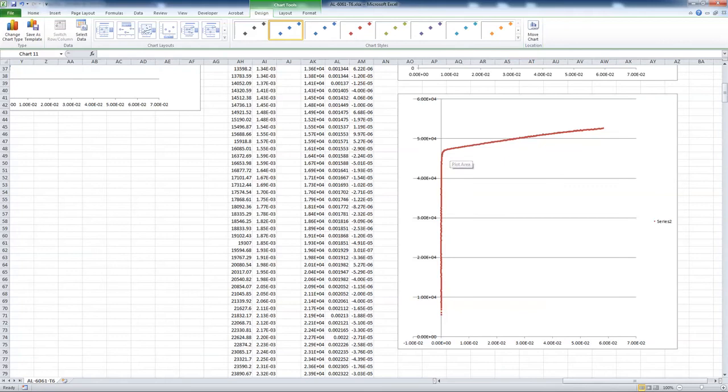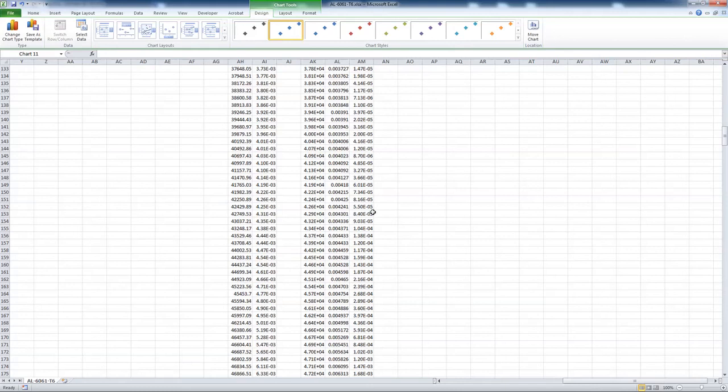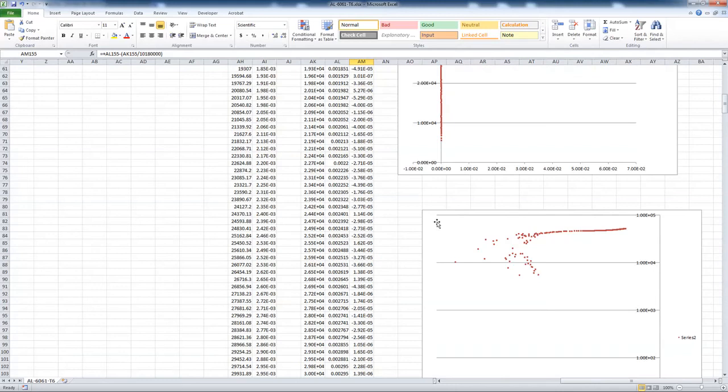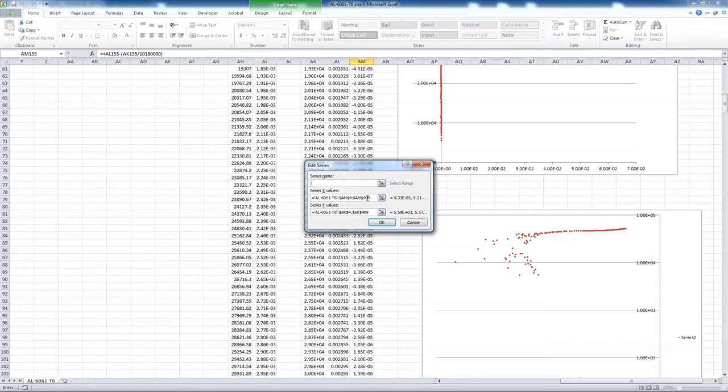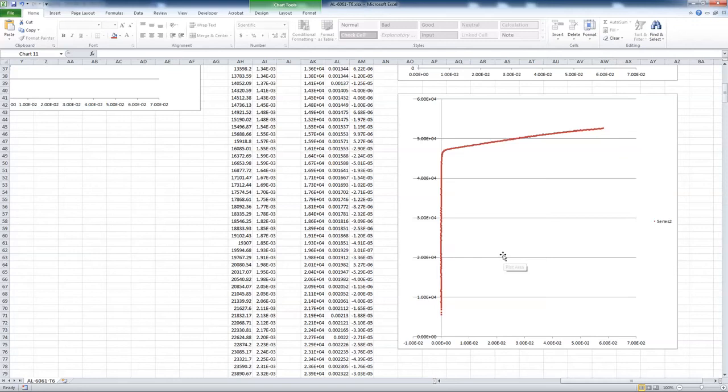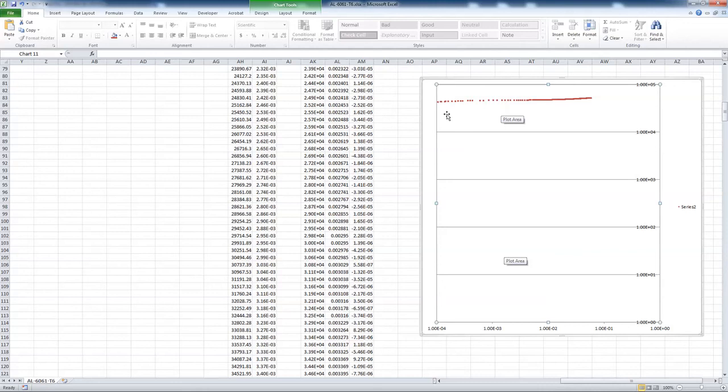Okay, so now, let's do one more thing. Let's copy this. Now, let's change these axes to log-log axes. I have some tiny values. Now, you see here where we're primarily in the elastic region, we have a lot of weird data. So, this initial portion of the data, I'm going to throw out. Really anything above your 0.2% offset yield stress, we're going to throw out. Now, I haven't computed the 0.2% offset yield stress in this video, but I do want you to do that for your homework. So, let's start our data at maybe about this value.